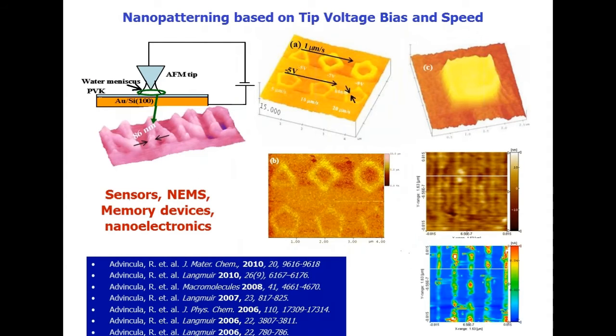On the other hand, we can access all the way to nano-level patterning. In this case, we demonstrated this work by using what we call a conducting AFM or current-sensing AFM method, where we actually polymerize, or rather electropolymerize, or even by Joule heating, created these patterns with sub-100 nanometer resolution using an AFM tip. So we demonstrated this nanolithography method utilizing this material that we reported, which can be patterned even at ambient conditions. In fact, one of the first works we did on this was in a high humidity environment like Singapore.